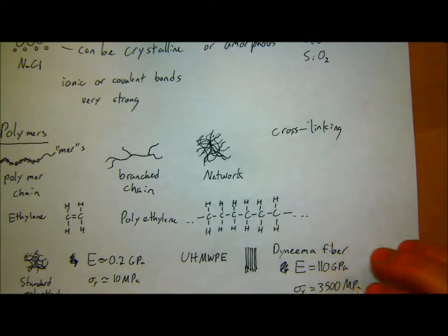So Dyneema, drawn out into these fibers, is incredibly strong axially in the fiber direction, but transverse to the fiber, these are all actually just held together with van der Waals forces. So there's very weak interactions holding them together. So if you shear one of these fibers, it has almost no strength. It almost falls apart, really. And if you get a stack of these, a Dyneema composite, which is normally how they're made, you can actually just peel the composite apart by hand because it's so weak. But in the direction of the fibers, you can't break it because just that fiber direction is incredibly strong. So yes, they're very, very anisotropic. So this is also an important consideration when thinking about the structure of these composites, or structure of the material, is how it affects the directions, not only in the direction you want, but also in the other directions. Thank you.